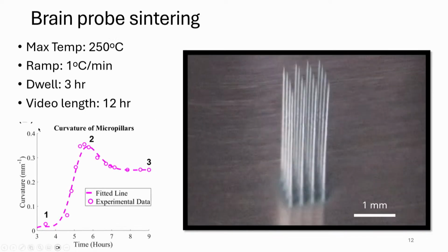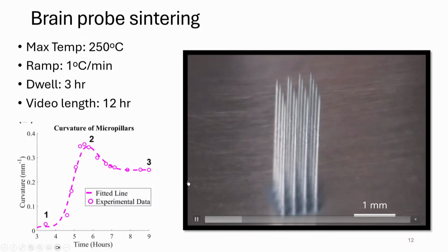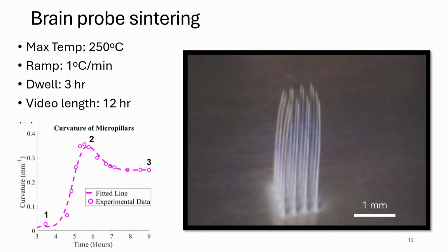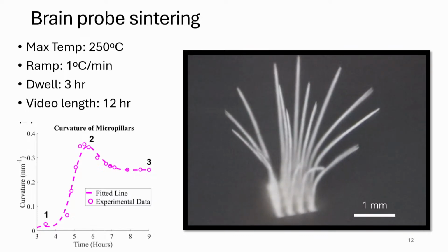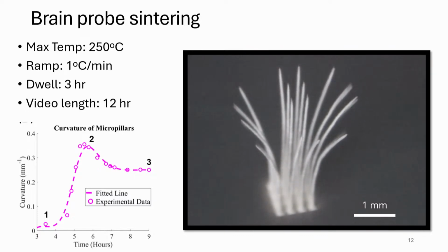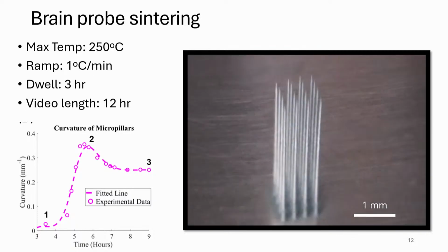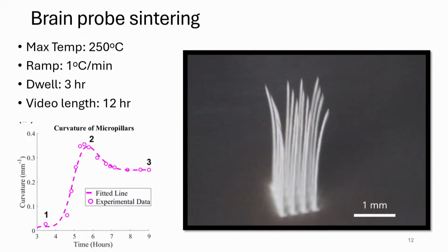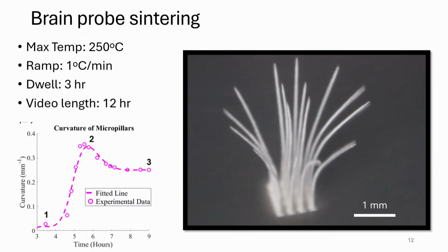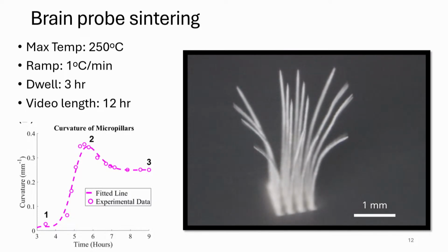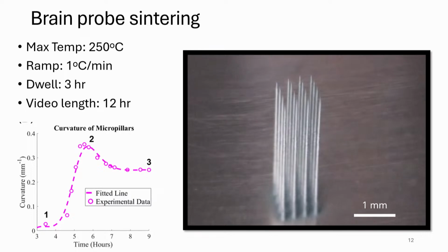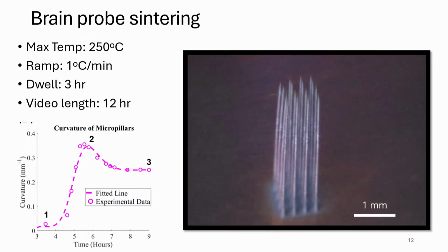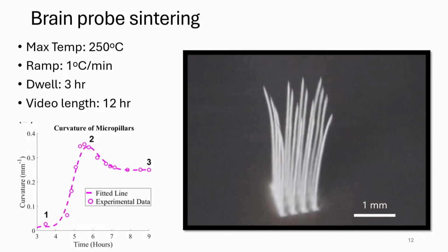We are going to deal now with a model which describes sintering and creep. I have already introduced you to what our main motivation for sintering is. For creep, you know what the motivation is. We need to model creep. We need to understand how polycrystalline materials creep. But this is additive manufacturing, 3D printing of, if I remember well, this was silver. So nanoparticles of silver, particles about 30 nanometers average size, are printed,